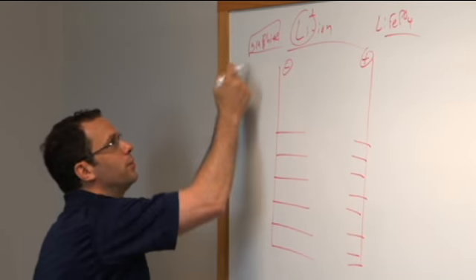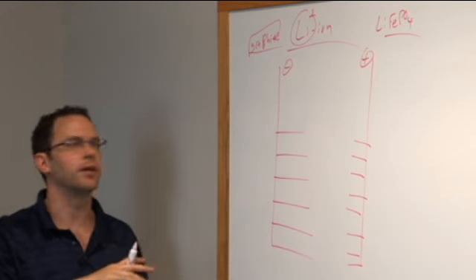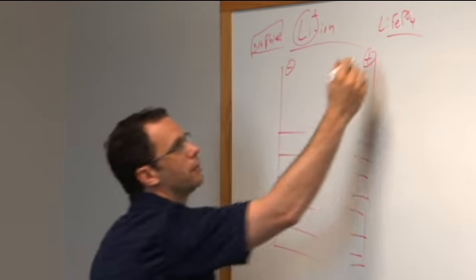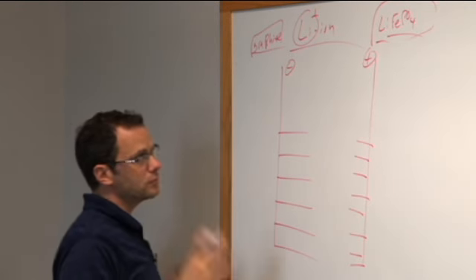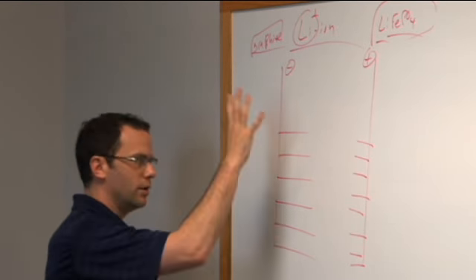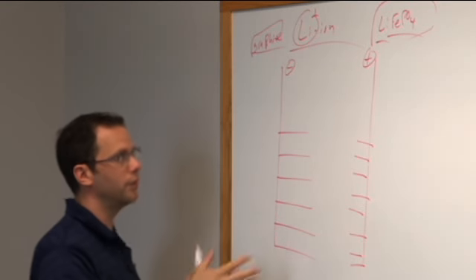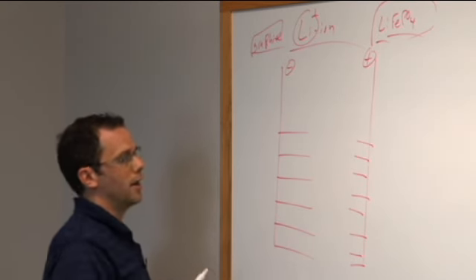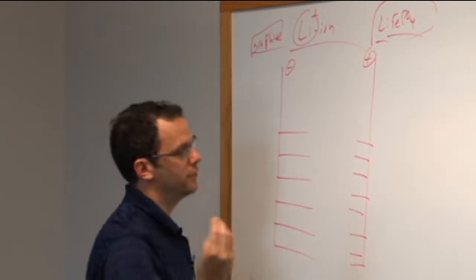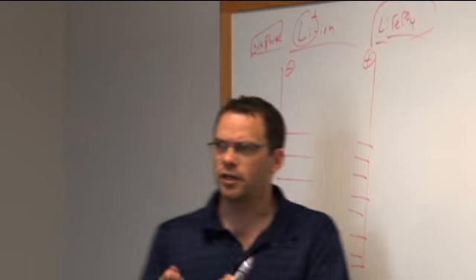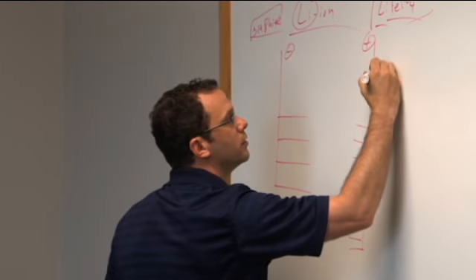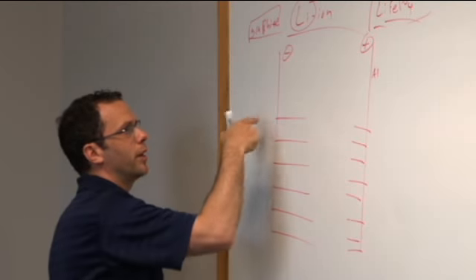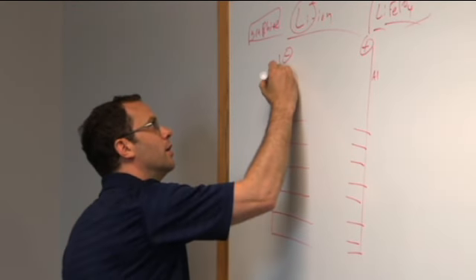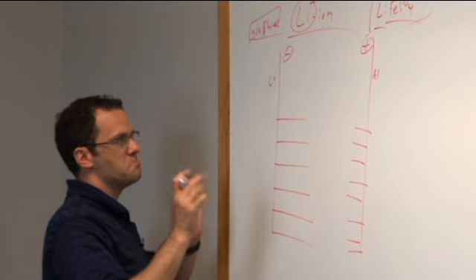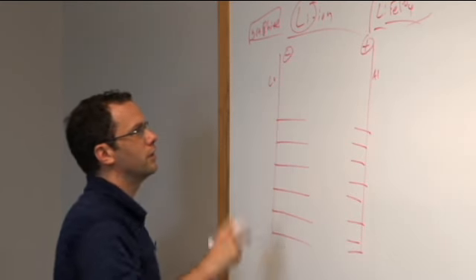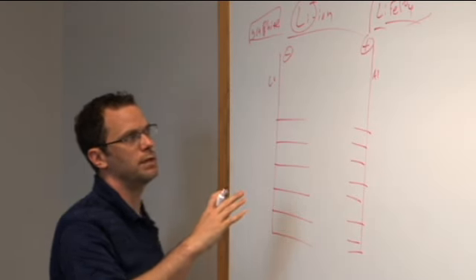Okay? Turns out that simple graphite, if you get the right kind, modified properly, with the right structure, can do that. And lithium iron phosphate also can do that. Okay? And when we make a lithium ion battery, the first thing we do is we put virgin graphite on a very thin foil on the anode side. It's never seen lithium before, and we take lithium iron phosphate powder or nano powder. It's spray deposited on a thin aluminum foil, and our graphite powder is spray deposited or cast coated onto a copper foil, and the thickness of my foils is probably under a mil, maybe 20, maybe 15 microns.